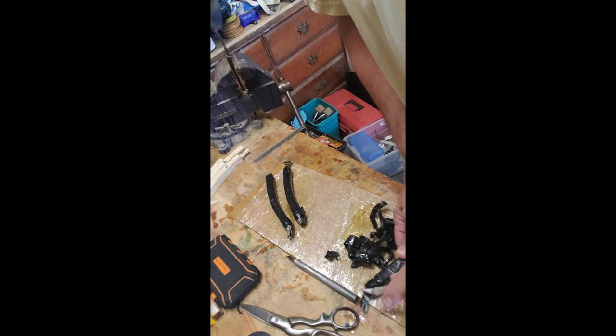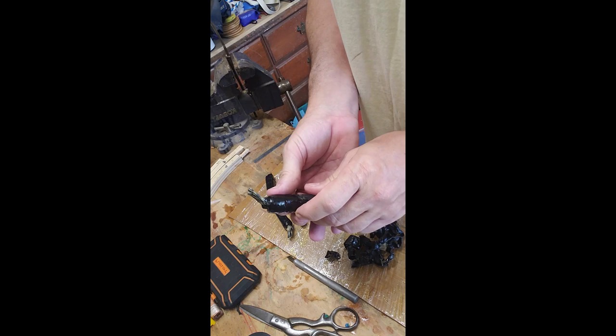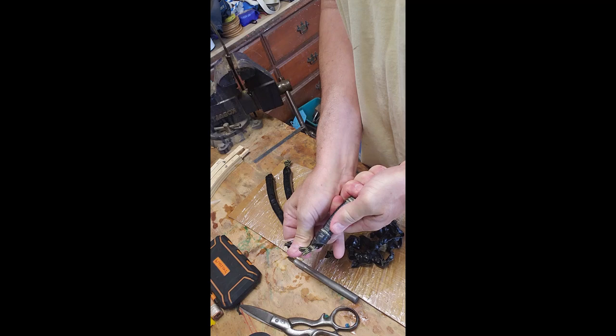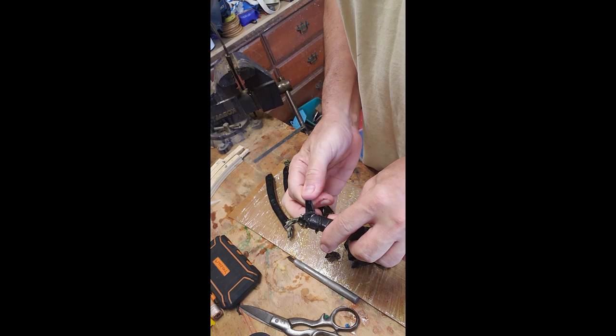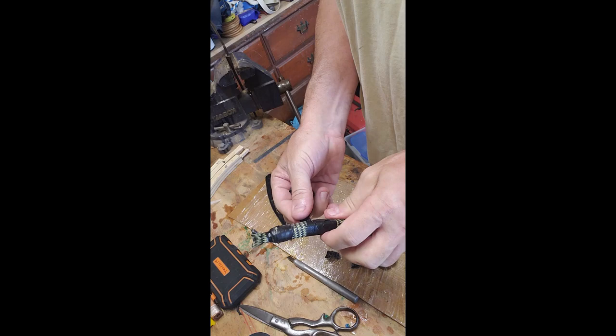So I think that this one-to-one epoxy that I'm using is a little bit rubberier in its final state than two-to-one, because if I do this with two-to-one, it just kind of flakes off and the whole thing comes unwrapped in a very satisfying way, and this is kind of rubbery, a little bit resilient, which is not terrible. I think it's still very strong. It's not quite as satisfying to unwrap, I guess. Not the most important thing in the world. Okay. There we go.